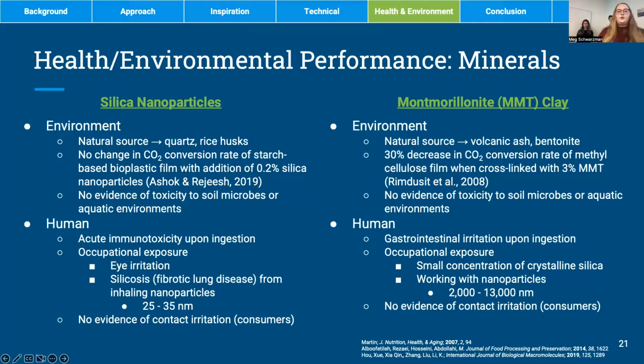So keeping with our same order that we've been presenting, we're going to look at minerals, which we broke into silica nanoparticles and montmorillonite clay. So some of our main takeaways here, looking first at biodegradability. We looked at a study which looked at the biodegradation rate of a starch-based bioplastic film, which contained 0.2% silica nanoparticles, and they observed no change in the rate of biodegradation with that addition of the silica nanoparticles. So a pretty neutral metric.